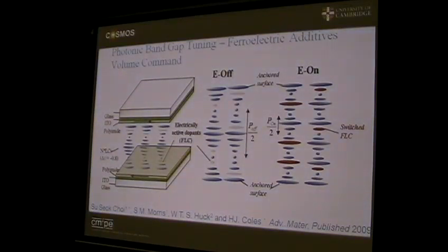That works. What we've done here, if you like, is the latest and greatest, is combine some of the ideas of liquid crystal devices and displays technology into the lasers. So what we've done is take a ferroelectric liquid crystal that phase separates in a chiral nematic. So it's a ferroelectric additive that is in the chiral nematic matrix. Okay, and that's shown by those little red blobs there, if you will. Okay, they're additives, dopants, ferroelectric dopants.